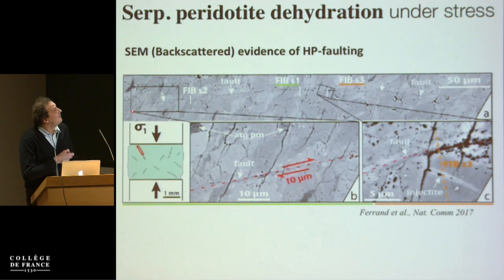So here is one image of a sample where you can see a fault trace. This is 50 microns. You see the fault trace. If you zoom here, you see it maybe better. You see that there is an offset of around 10 microns. So we're talking about really a magnitude -6 or -9 earthquake here. And if you zoom in this place, you still see the fault trace, and you see this little thing here that we will come back to later on.